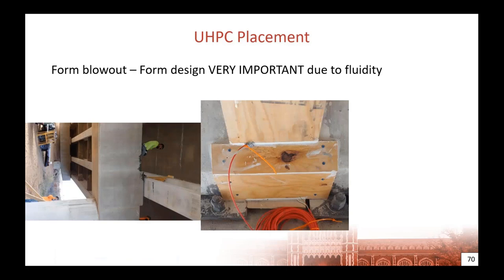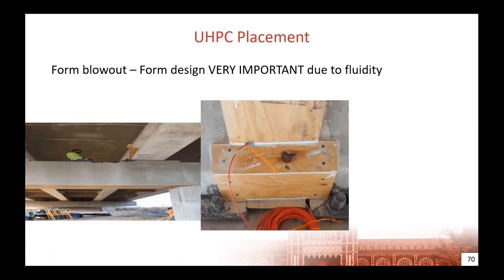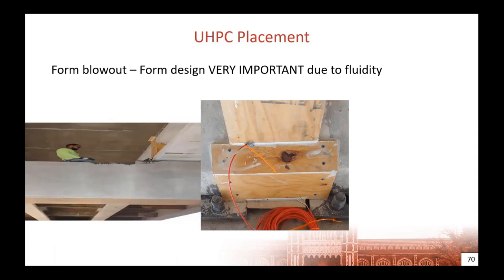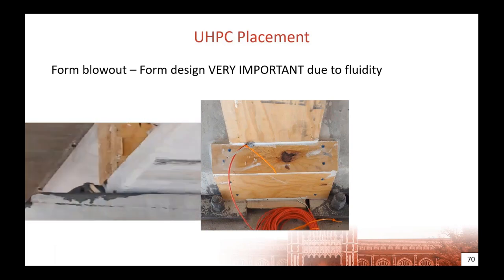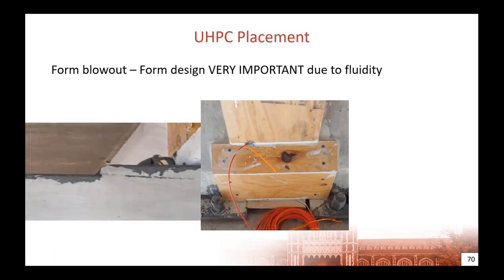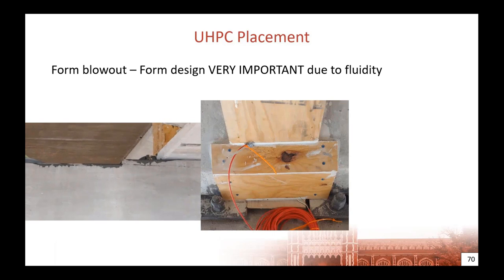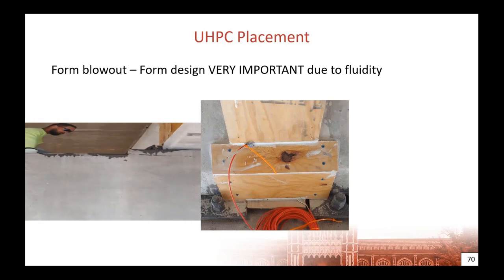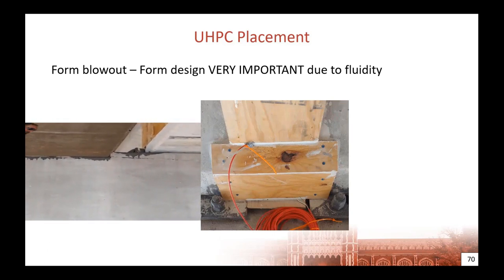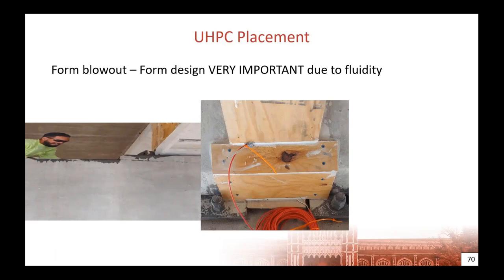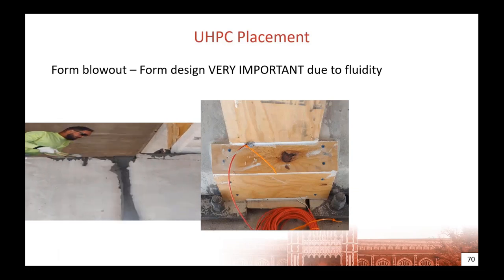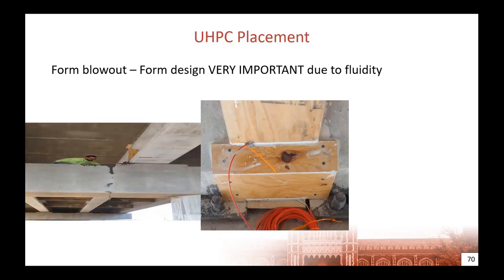But unfortunately, we did have some issues, as I mentioned. The first attempt at the concrete pour went smoothly for a little bit. They managed to fill up an entire form, and then we had a form blowout. That bottom piece of board that you see on the right popped out because it was attached with TAPCON screws, and the TAPCON screws failed and blew the form out, and they lost all the material out of that joint. So they had to redo it.